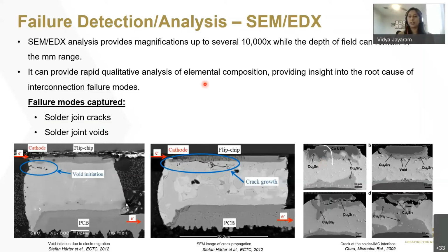As you can see here on the bottom right picture, it can give insight about different atoms, elements, and the intermetallics that are formed. So the typical failure modes that you can capture with this would be the solder joint cracks and voids. But more than capturing the failure mode, I think SEM combined with EDX is a very effective tool to understand the root cause of the failure.